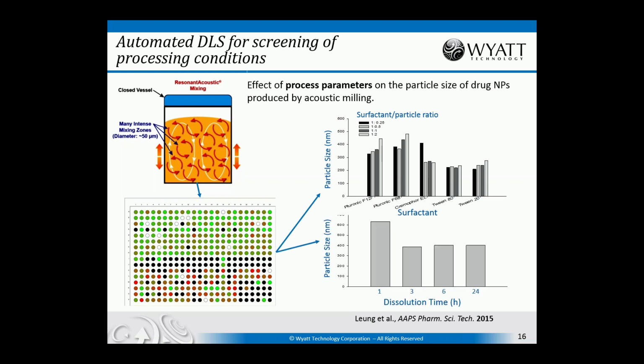the dissolution time, so for how long they were applying this process. And in this data, there are also the different types of buffers that were tested. By setting up this completely automated system with the different acoustic resonant conditions and formulation conditions on the one hand, and the automated measurements on the other hand, they could complete in the course of a few hours what otherwise might take weeks by standard techniques. And so the gain in productivity that you get with high throughput DLS can be measured in terms of reducing to less than a day what might take many technicians many weeks to accomplish using standard dynamic light scattering in cuvettes.